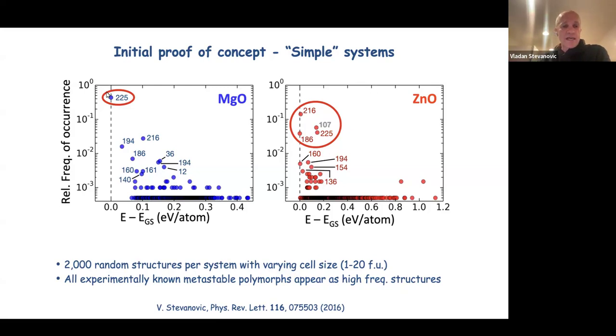In the case of magnesium oxide, this one that occurs 50% of the time, so literally 1,000 times out of 2,000, is the ground state rock salt structure. And this fact corresponds very well to the experimentally known fact that magnesium oxide has been realized experimentally only as a rock salt and nothing else. So magnesium oxide doesn't really have any polymorphism. No structure other than rock salt has ever been grown.